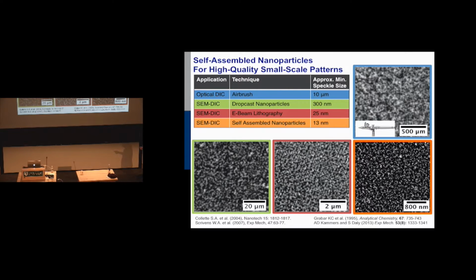So then we tried drop casting nanoparticles. So we were drop casting them and basically taking nanoparticles in solution and spinning them. And the problem with that was this is totally cherry-picked. What happens when you drop cast nanoparticles on a specimen is they immediately coffee ring, just like when you put your coffee down on the table, you'll form a ring. So there's areas where the density is great for deformation tracking, but you'd have to go around and cherry-pick the area, and everywhere else would not be very good.